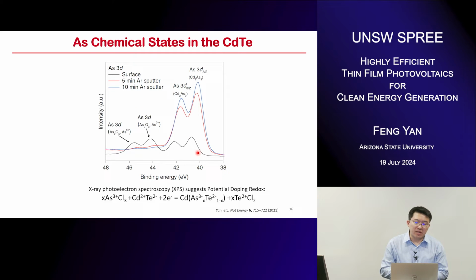Looking at the chemistry, we can find another interesting thing: if we want to occupy the tellurium site, it prefers an anion inside the system. But we're using a cation in the arsenic chloride. How this reduction occurs in the system is still a little bit unclear, but per the chemical state understanding, it seems that the arsenic 3 plus cation is reduced to arsenic 3 minus, which is pretty promising. We are working on this, trying to understand the process.